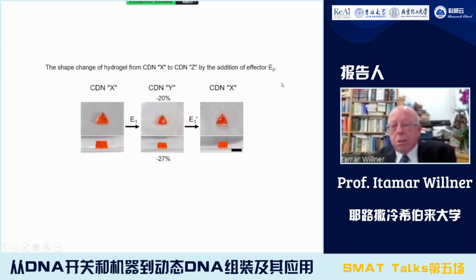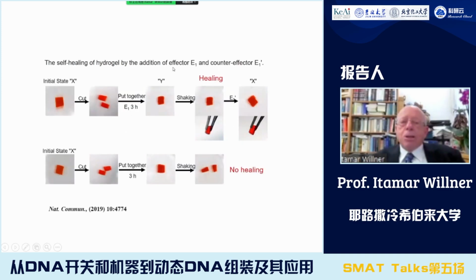What can we do with it? First of all, we can show it demonstrated visually. You can see this is the medium stiffness. When we go to the higher stiffness, a shrunken hydrogel is formed that shows a decrease in the volume by about 20%. But we can use this property of controlled stiffness to introduce some functions.